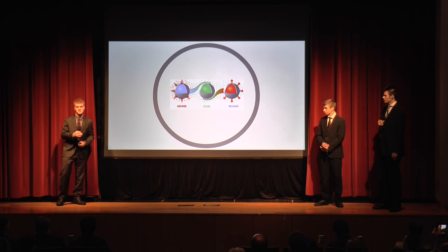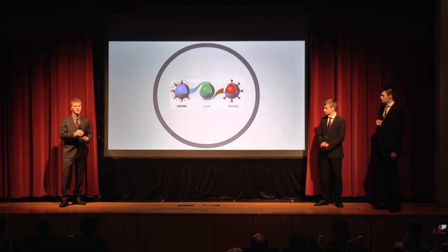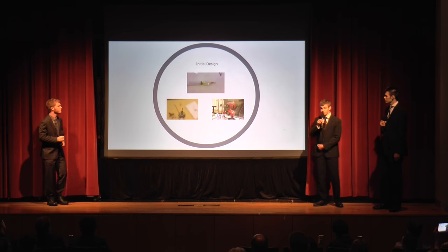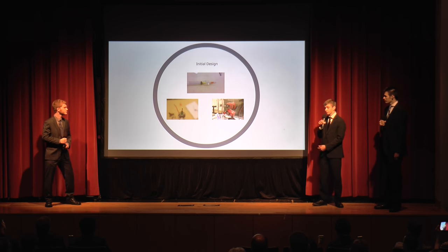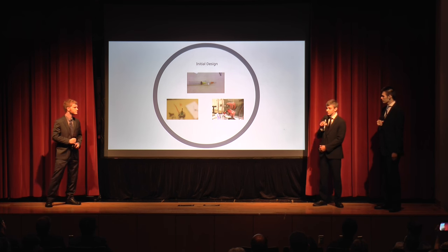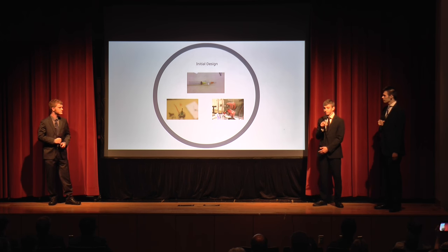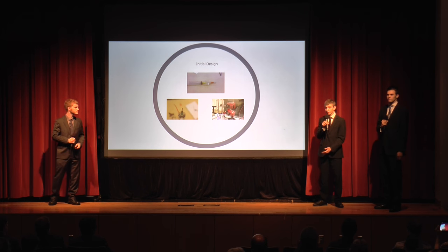As Delta Phase Enterprises, we wanted to improve on this. Instead of a shell or a spherical formation like this, we wanted to create a phase change material in a nanofiber by core sheath electrospinning, like Nanomedical talked about, by having one nanofiber inside of another, where the inside nanofiber would be the core material, the outside shell being the sheath. To successfully core sheath a nanofiber, we needed to do something called coaxial electrospinning, which is achieved by having one needle within another needle. That allows one polymer to pull the other all the way to the collection plate to have a fiber within a fiber.